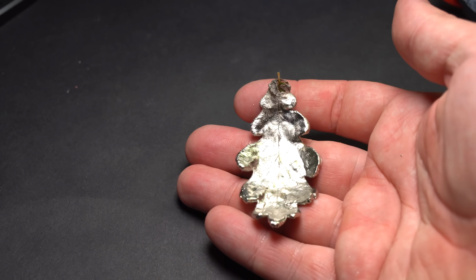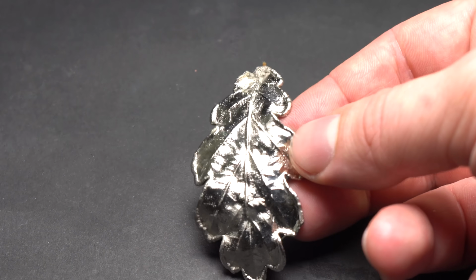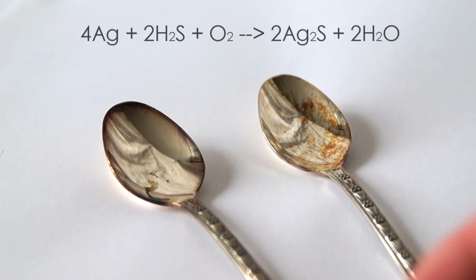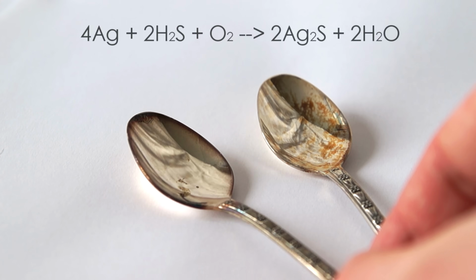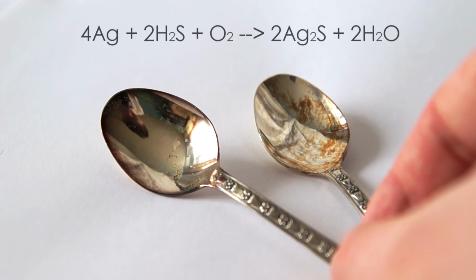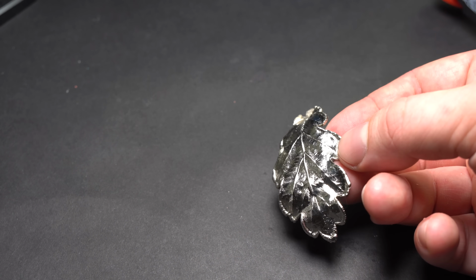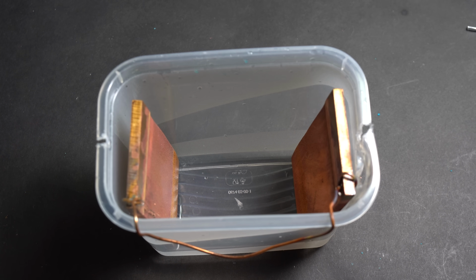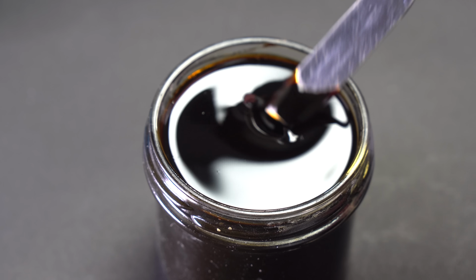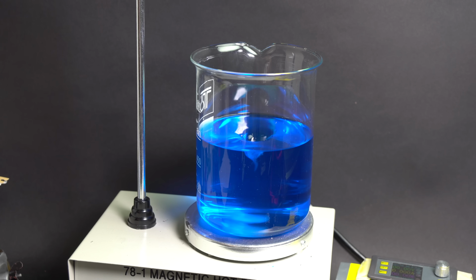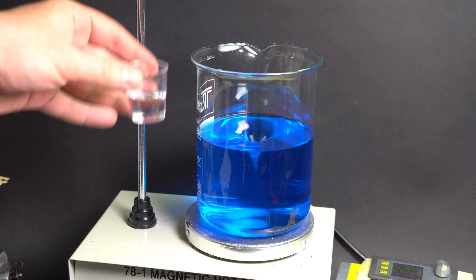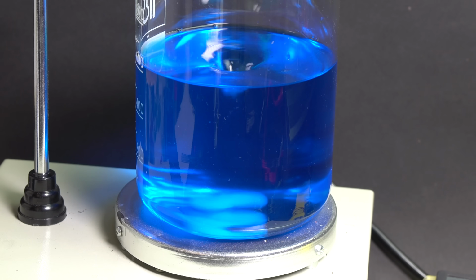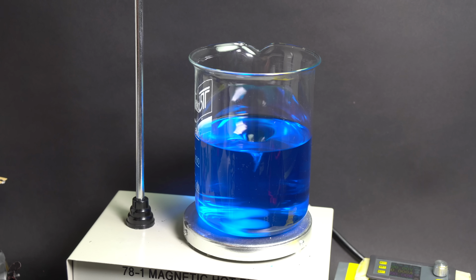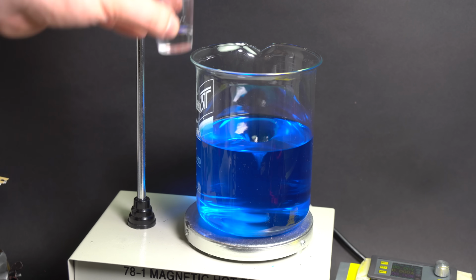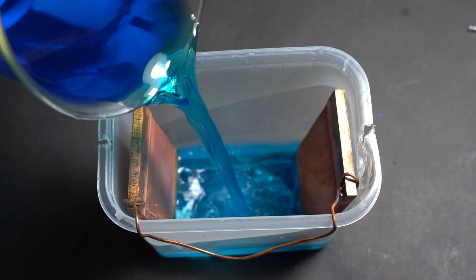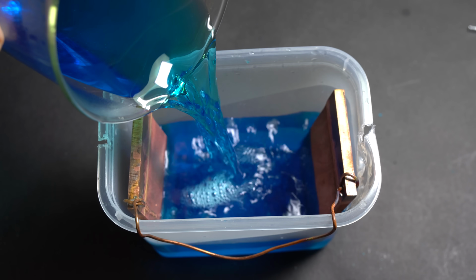By the way, in my opinion, there is no need to silver plate such a leaf, because in time silver oxidizes and fades in the air. The only thing I do not like about this leaf is that the copper layer is too thick. That is why I decided to change the electrolyte in the big tub to a well-proven one and not to use black treacle. I made a new improved electrolyte from 100 grams of copper sulfate dissolved in 500 milliliters of water. Then I added 70 milliliters of concentrated sulfuric acid and 3 milliliters of ethanol as a surfactant to this solution, to improve the surface, with a little bit of gelatin dissolving it.